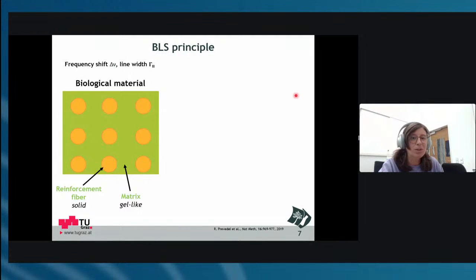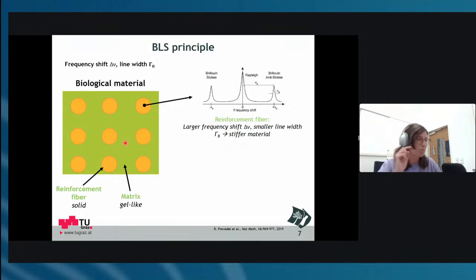Yes, so before we go into examples, I want to show you a little bit with this simple sketch what you can expect from measurements. So I mentioned we are always getting the frequency shift and then also the line width of the peaks. And when we take a biological material or a composite material, it doesn't really matter, and it consists of a reinforcement fiber, which is more solid, and the matrix around it, which is more viscous and gel-like. If you do measurements here, let's say we really make a spot just on the reinforcement fiber. I mean, this is just an ideal illustration. In reality, this cannot be the case, I would say.